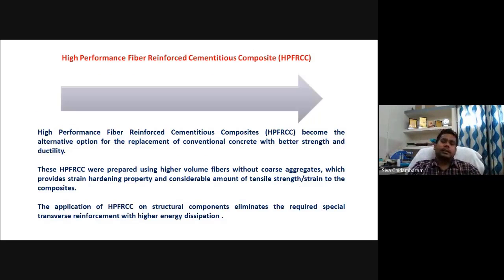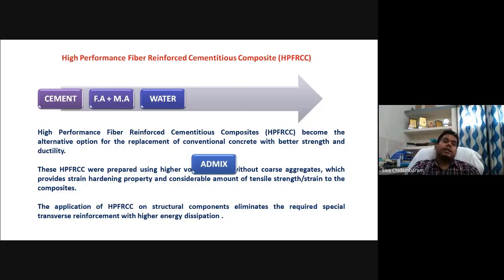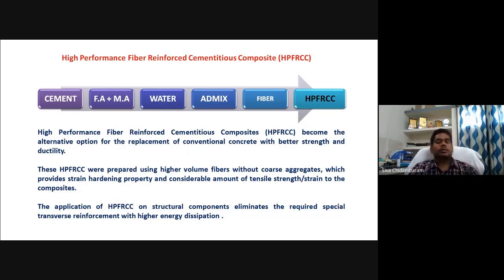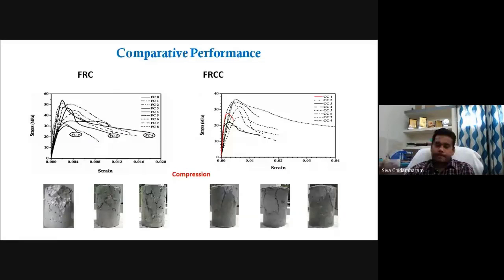Another one is called fiber reinforced cementitious composite, in which we have cement, fine aggregates, mineral admixtures, and chemical admixtures plus fiber. Here I am not using coarse aggregate. Why am I not using coarse aggregate? Coarse aggregates are the very big culprit in deciding the dispersion capacity of your fiber. When you use coarse aggregate, that significantly affects the fiber dispersion property. Number one, it's the main culprit. That's why in conventional fiber reinforced concrete, we are not able to go more than 2% of steel fiber.